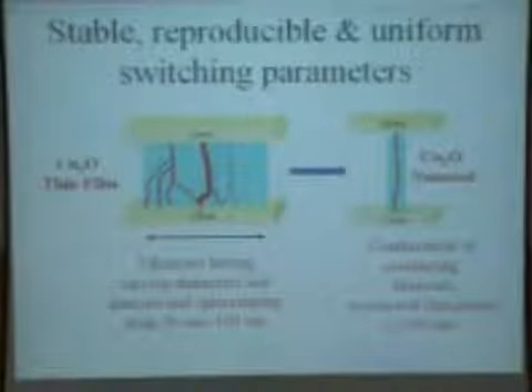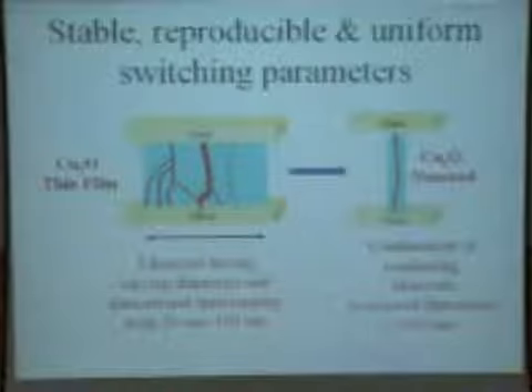What is the advantage of using copper oxide nanorods in place of a copper oxide thin film? Each nanorod acts independently. We don't have a thin film now, but a parallel network of copper oxide nanorods. Each nanorod is electrically isolated from the others, there is a gap between them, and on the surface of each nanorod there is some alumina template. You can always keep the etching condition such that some alumina remains on the surface of the nanorod, so that they are not electrically touching each other.